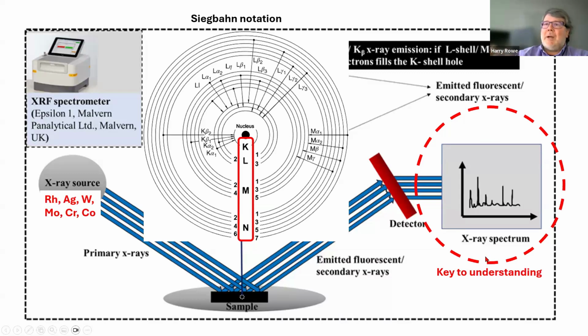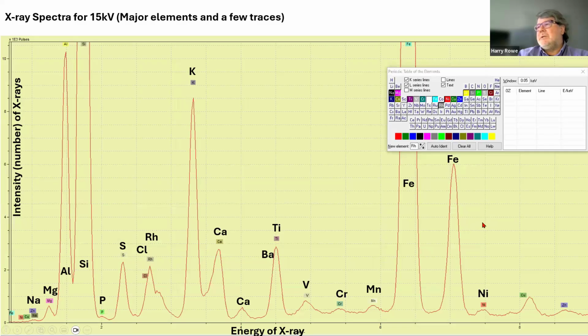I'll give you an example: barite. If you don't get all the barite out, or if you don't get the majority of the barite out, it wreaks havoc with calcium, titanium, vanadium, lots of elements that people like to look at. So we really need to understand those inter-element corrections. We're not able to constrain them properly. You can see here barium. I don't have to show the peak, but barium lives around here, and titanium is right next door. Getting a good titanium analysis really depends on getting that barite down.